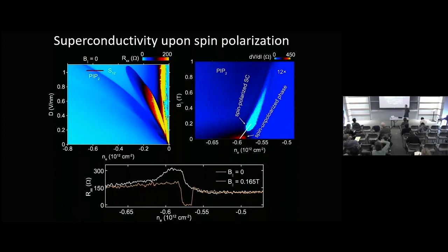So is the experimental data only with in-plane fields, or do you also tilt the field out of the plane as a function of angle? You can put the in-plane field, then you make the superconductor, and then if you put even a little bit of out-of-plane field, you kill the superconductor right away. Thanks.